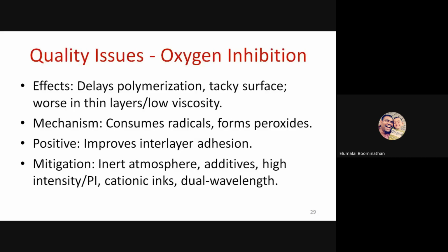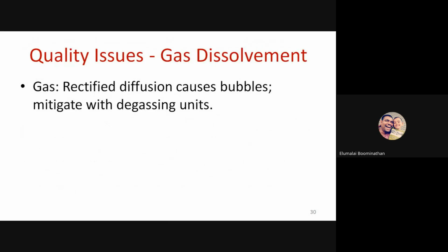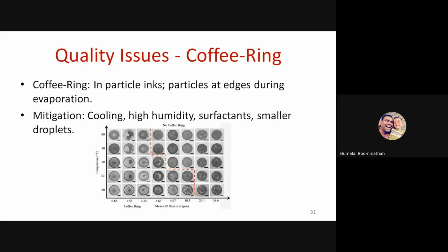But the top layer, if you're having oxygen inhibition, the outer surface will be tacky. So you have to optimize the oxygen inhibition. That's why we are going for hybrid inks. So beyond shrinkage as well as the oxygen effects, there are issues like gas dissolvement, where the bubbles are trapped with gas. So it leaves pores inside the printed product. Or we have a well-known coffee ring effect, where the particles in a single droplet migrate to the droplet edges during the evaporation process. So it causes uneven deposits.